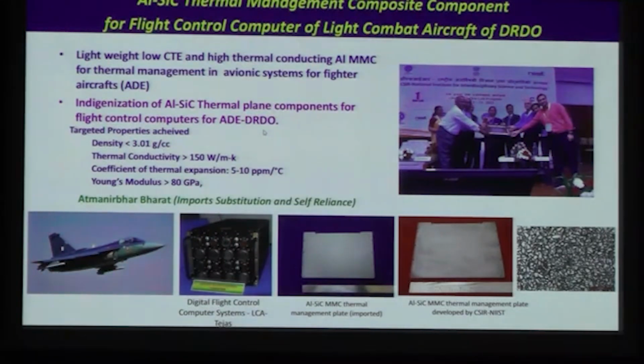and 4 plates are being used. The target properties are density less than 3.01 gram per cc, thermal conductivity greater than 150 watts per meter Kelvin, coefficient of thermal expansion of 5 to 10 ppm per degree C, and modulus of greater than 80 GPa.